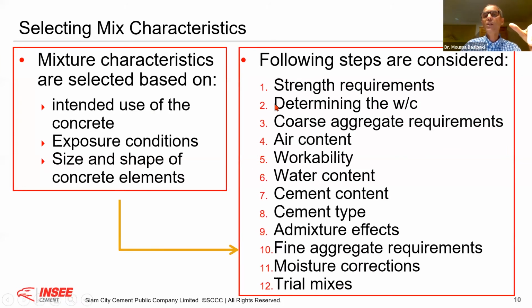Now, this is why we will go through what I call the important steps. We start with step 1. As an engineer, I need to know what is the strength requirement. This I cannot invent. I should know the strength required according to the design. After that, there is one important element, that is the water cement ratio. Because there is a very simple law in concrete technology, up to 50 megapascal. There is a linear relation, they call it the Feret relation or the Abrams relation, where the water cement ratio is linear with the compressive strength. When you reduce your water cement ratio, you increase your compressive strength, or when you increase your water cement ratio, you reduce your compressive strength. Therefore, it's almost linear. And there is no universal one. It will depend on the raw materials, cement, aggregate, sand that you are using, and the mix.